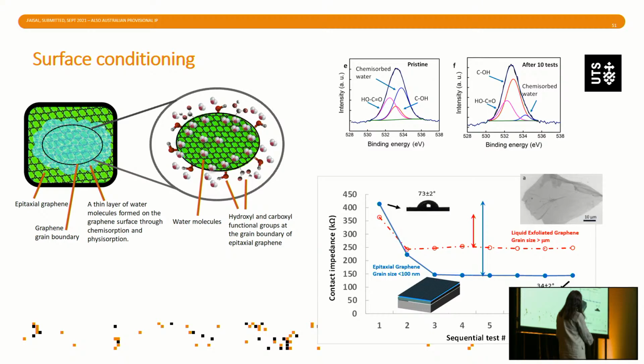And because of that, that story of the intercalation and the increasingly better contact with the skin and a high conductivity as a sensor would not be as good. But because we have small grain sizes and we can functionalize them in situ, in the presence of water, we basically go from a high contact angle, initially of over 70, down to 30 and something after contact with the skin.